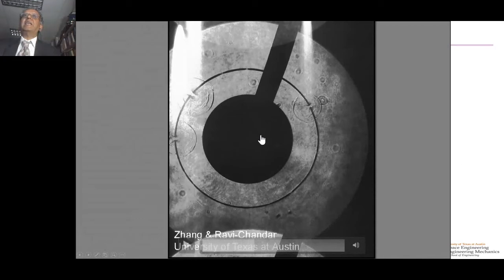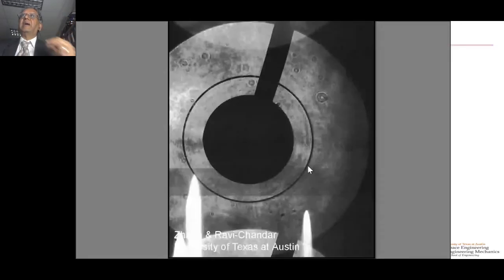If you used any other kind of diagnostics on this, for example, you use a VISAR reflecting off of the surface of this thing, you would measure the velocity of this. This is a very common measurement, but it will give you the kinematics of the problem. It doesn't say anything about when the fractures occurred and what sequence they occurred in.